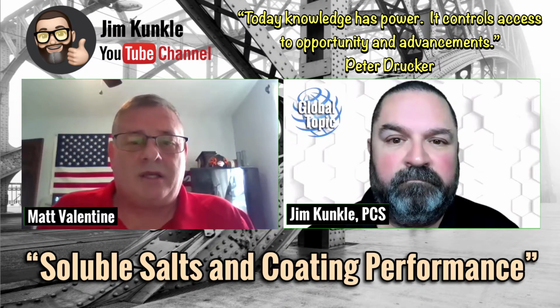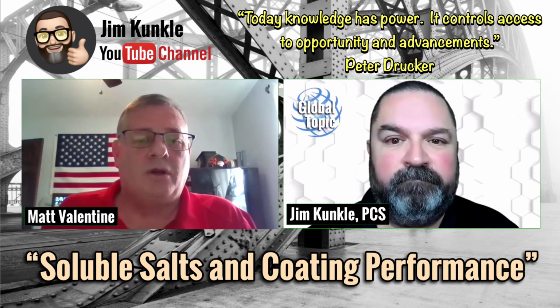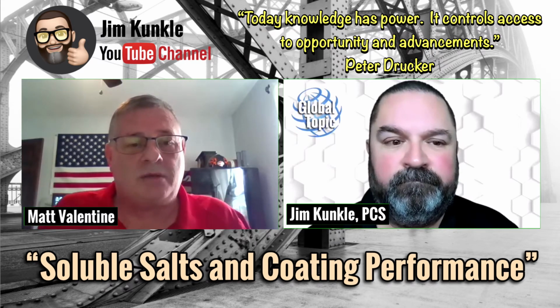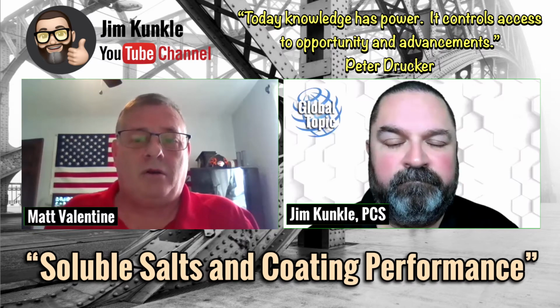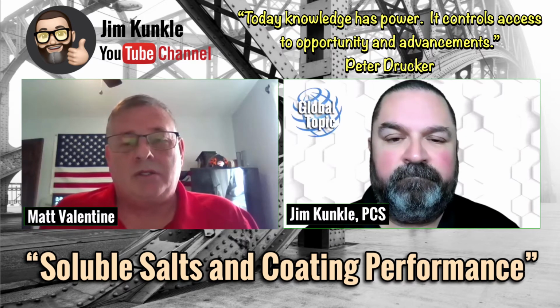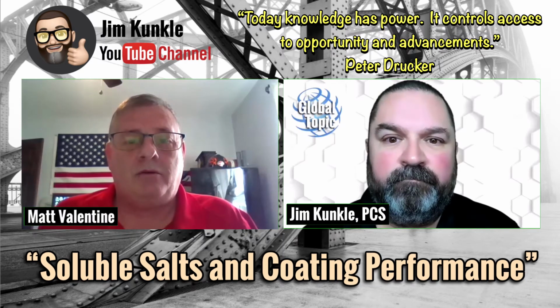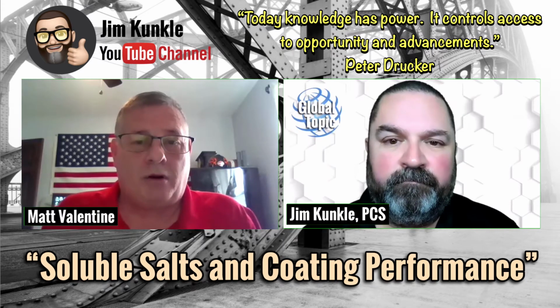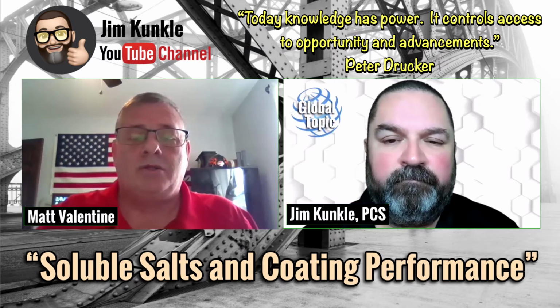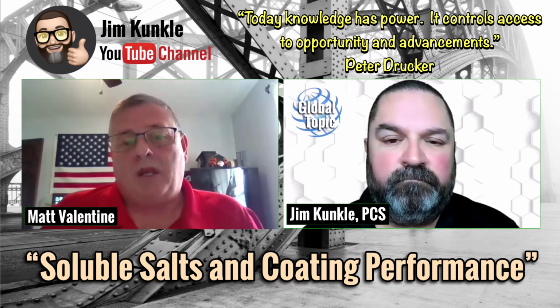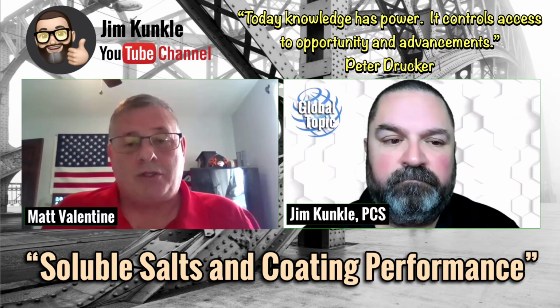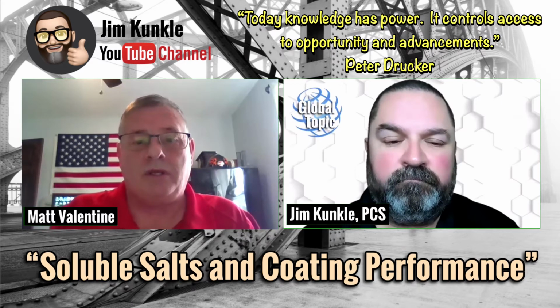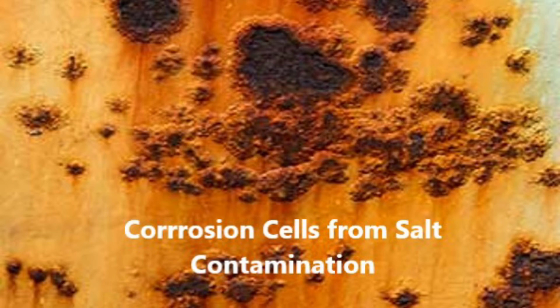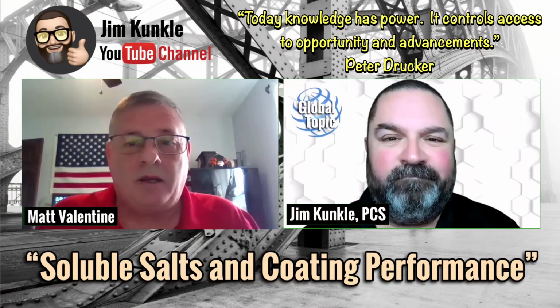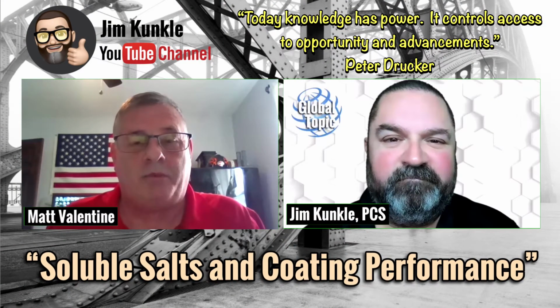Typically, if you're not testing for salts, you risk the possibility of coating over the salt ions that are attached to the substrate, which creates a premature coating failure. That's typically because most coatings that are applied in any aspect of the industry are permeable to some degree, some more so than others. So when you have the salt ion underneath the coating, and moisture passes through the coating system, it reacts with the salt ion and creates a corrosion cell. I think everybody's had to deal with the salt shaker in a highly humid area where they always have to put rice in it to keep it from clumping up.